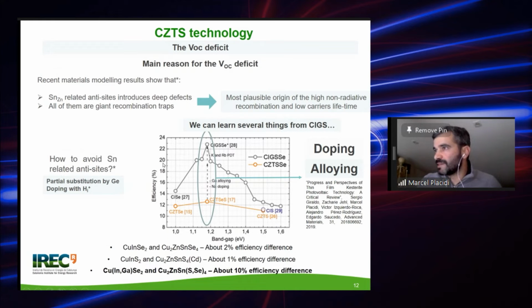If we look, for example, at this graph showing the efficiency as a function of the band gap, we can see here the pure selenide chalcopyrite and kesterite show an efficiency difference of 2%. If we see the pure sulfide side, so the high band gap side, we see that this difference is even lower, 1%. But here in the middle, we can see a large difference of more than 10%.